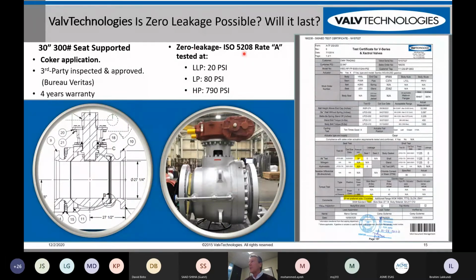And you can see that we performed testing with the acceptance criteria of ISO 5208 leak rate A. With nitrogen testing at low pressure, 20 psi, after 4 years of coker service, the valve still is bubble tight, zero leakage. We then increased the pressure to 80 psi. The valve held just fine. Those results you probably can't see, but again, we'd be happy to provide you with a copy of this. You can see the third-party witnessing and that there was zero leakage.